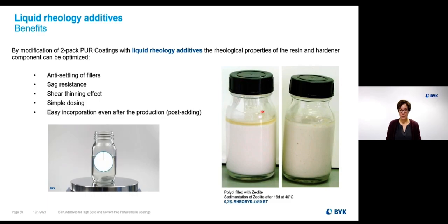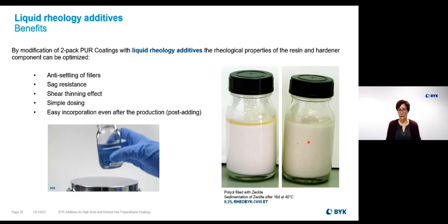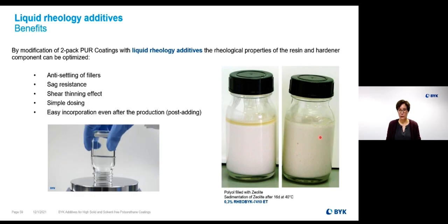Here we have again an example: sedimentation of zeolite after 16 days in a 40-degree hot box. On the left-hand side, you see that you have a small sedimentation. On the right-hand side, using 0.3% of Rheobyk-7410 ET, you do not have any sedimentation or syneresis.